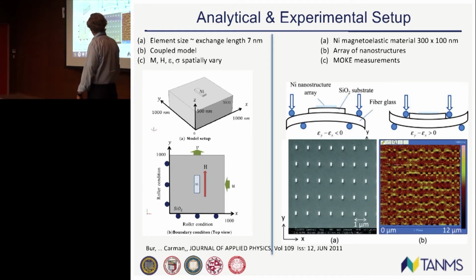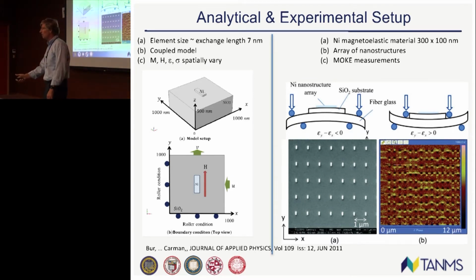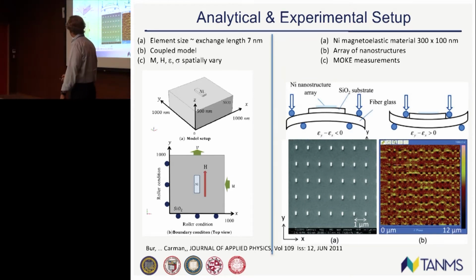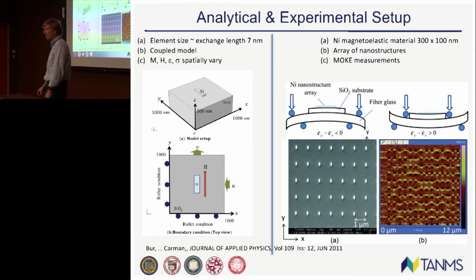So here on the left, you have an SEM image. You see those white dots? That's nickel domains. Over here on the right, you see this is an MFM image. You see that white and black region? That means this one nickel dot here actually has a single domain structure. So now we've gotten rid of all domain walls. So if you're a little ant here, you actually see the North Pole exiting that soft material.